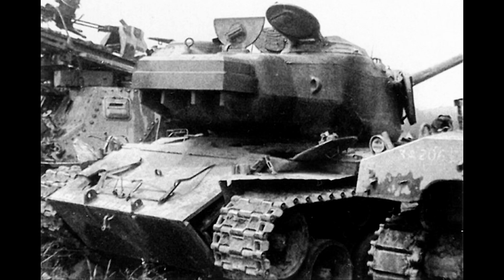The hull modifications were only part of the protection package. The turret required even more extensive work. Fisher engineers designed an entirely new turret casting based on the T-23 turret that would later be used on 76mm gun Shermans, but significantly up-armored. The new turret had armor 6 inches thick on all sides. Front, rear, and side walls all received 152mm of protection. This was equal to the frontal glacis plate of the Tiger II, Germany's newest and most heavily armoured tank. The turret sides alone had more armour than the Tiger I's frontal plate.